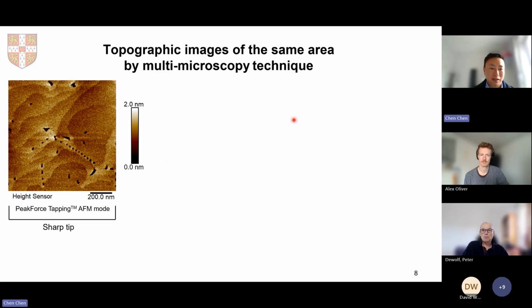So first, let's have a look at our sample. This is a high-resolution topography image of our sample surface collected using a sharp tip. As you can see, there are a lot of fissures on the surface. The question arises: what's the impact of these fissures on local threshold voltage? We are going to use additional techniques, conventional SEM and also hyperspectral SEM, to investigate that.